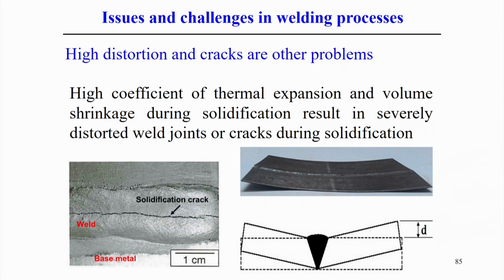That is another problem. Specifically, this problem is related to the large volume shrinkage during the welding process, and it depends on the typical properties of the material. If you look at the figure on the right hand side, it is a simple joining of titanium alloy by welding, and if the plate is very long we can observe some distortion. That distortion is related to the amount of residual stress generated within the body itself, and finally it creates the distortion.